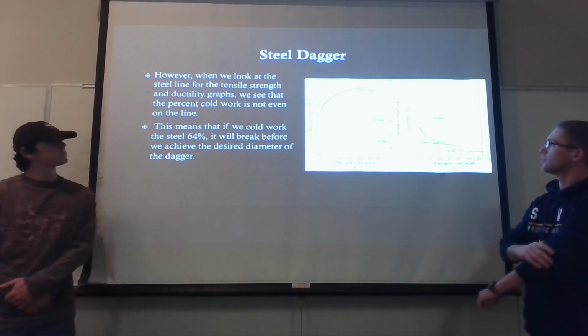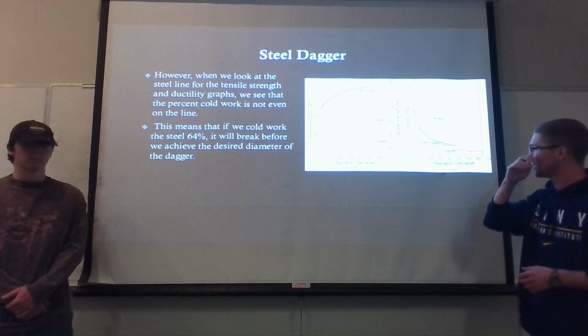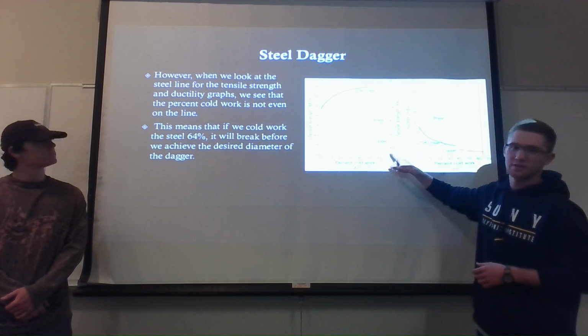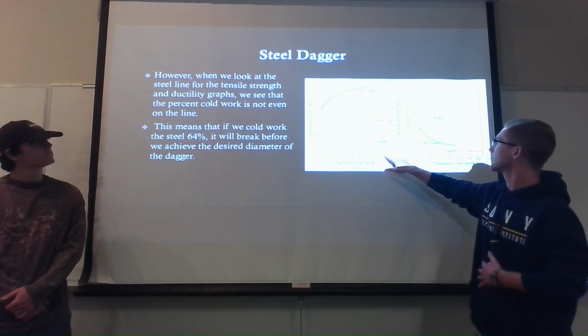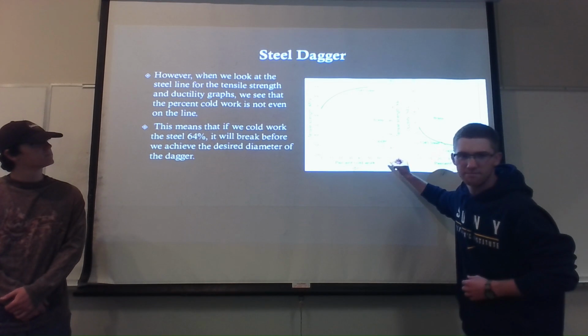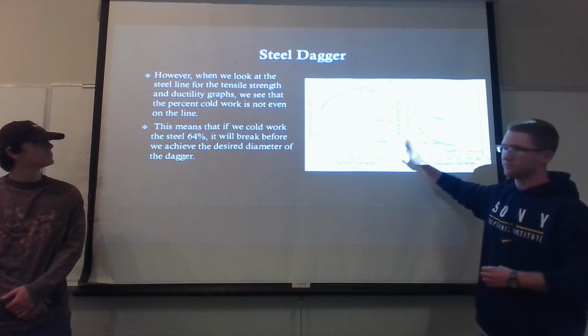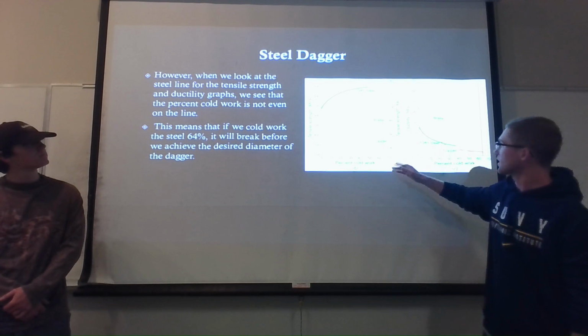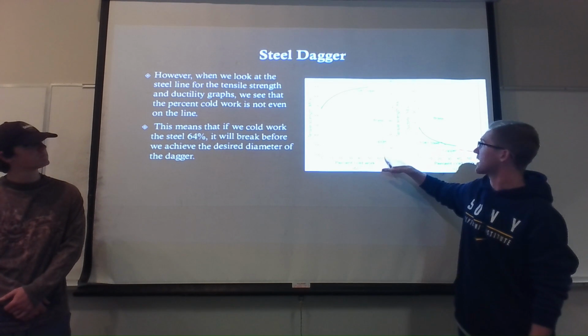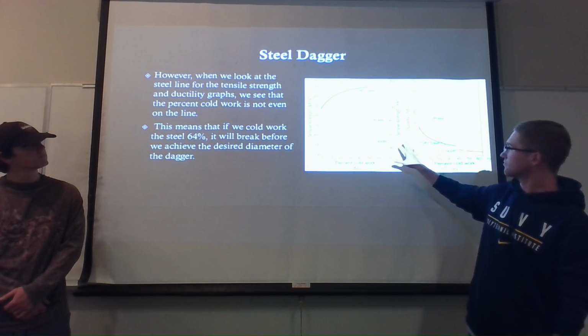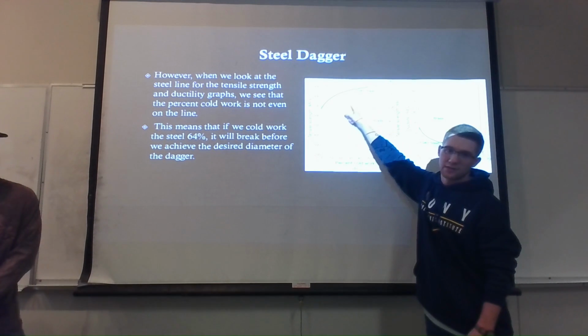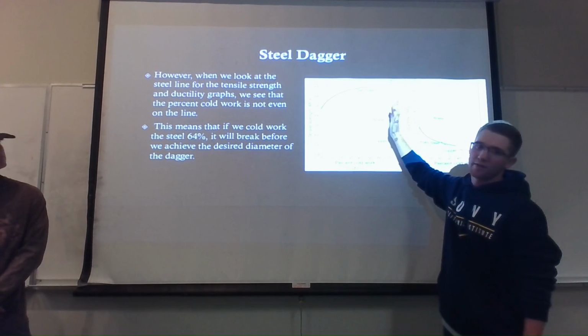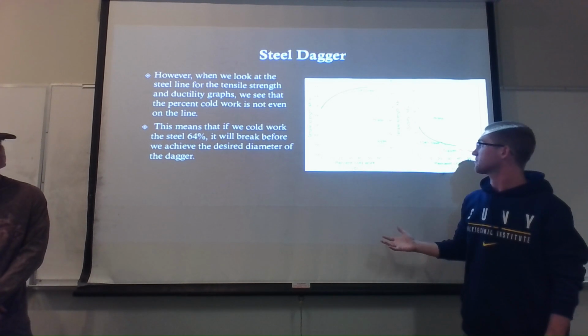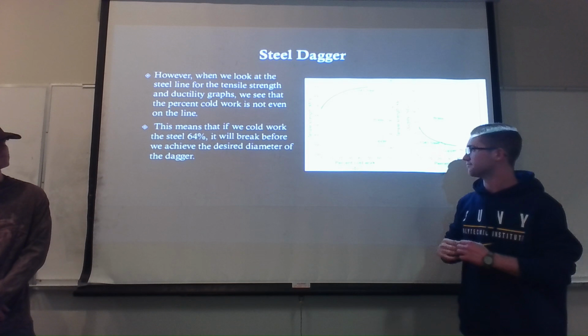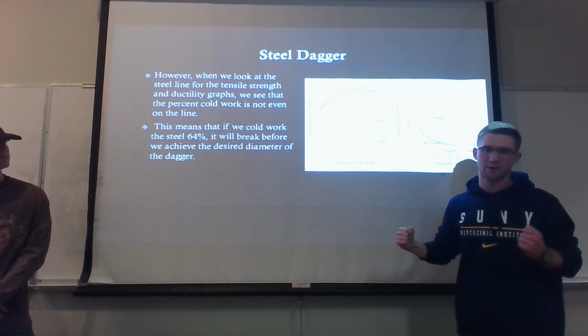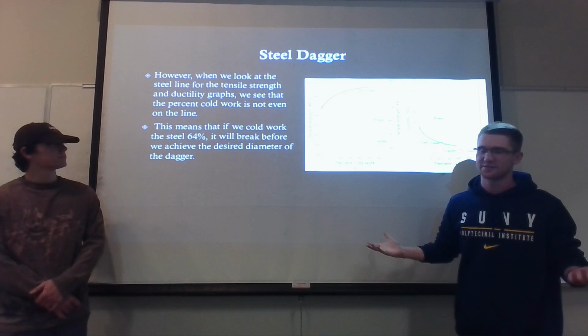So when we compare it to our graph for steel, we see that this line here represents the cold work, which it is. You just can't see it, but it's there. So the line for our cold work at 64% on both of these doesn't match up with the steel line at all. It is completely off. And so in this situation, the steel is broken. We've stretched it or cold worked it far enough to where it has just snapped. It's broken. It's done.